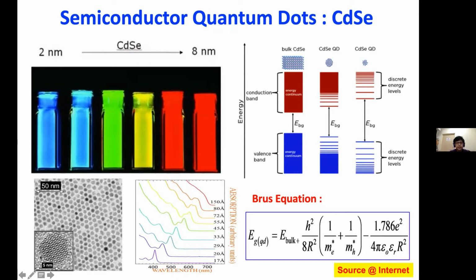Here you see some TEM images of cadmium selenide quantum dots. These small dots are cadmium selenide atoms, and here is the absorption spectra. Interestingly, for 17 angstrom, that means a 1.7 nanometer quantum dot, this is the violet color, and here for the 15 nanometer quantum dot, it is red shifted. So if you reduce the size, it is blue shifted. That's the interesting phenomenon when we reduce the dimension of nanomaterials.